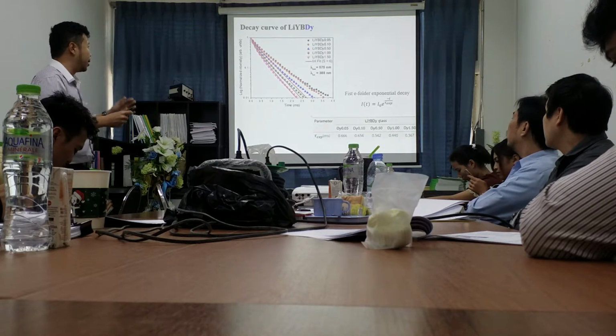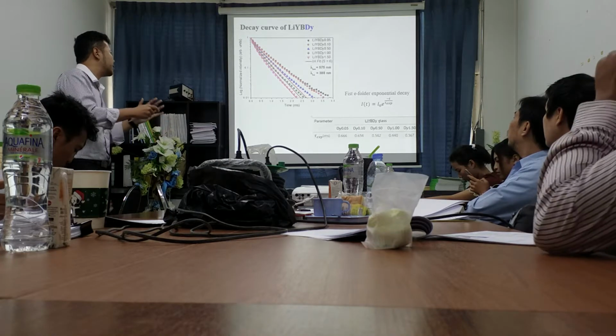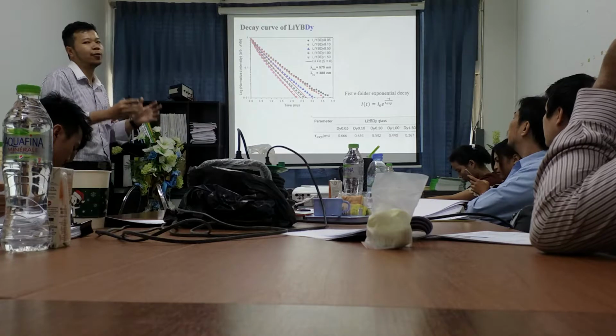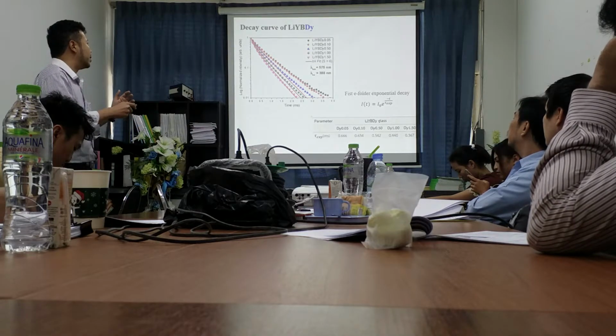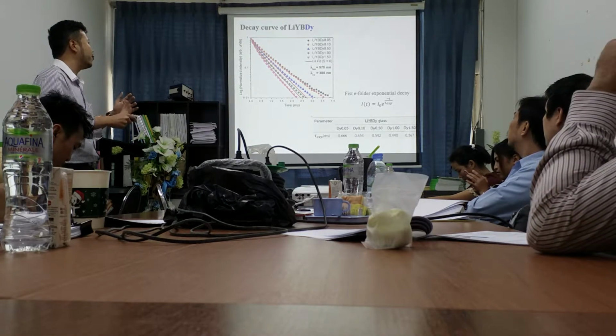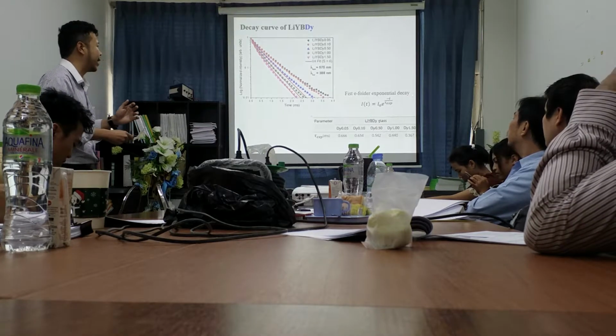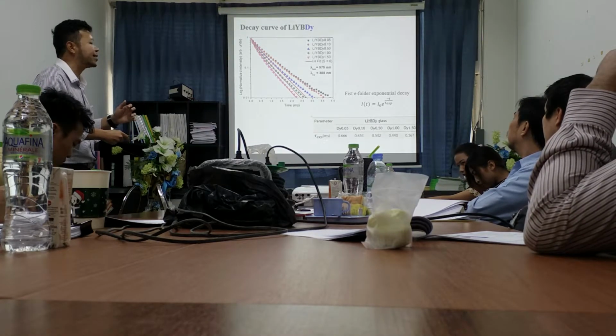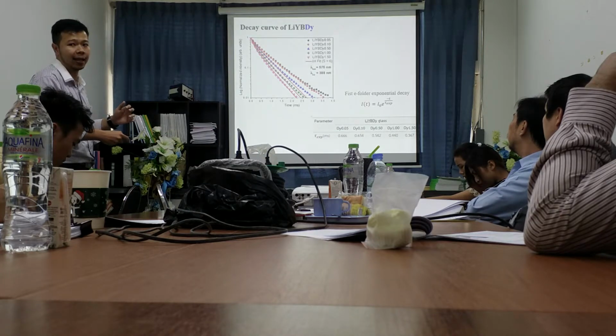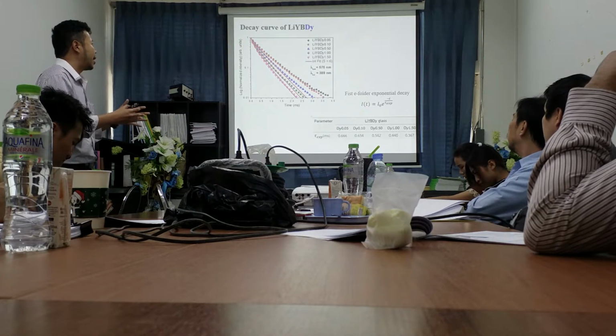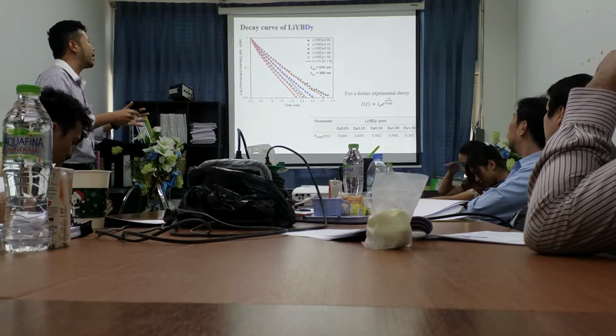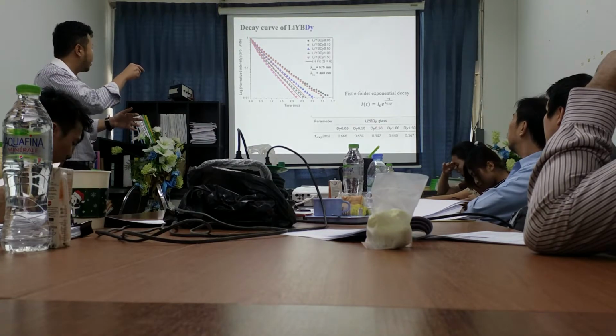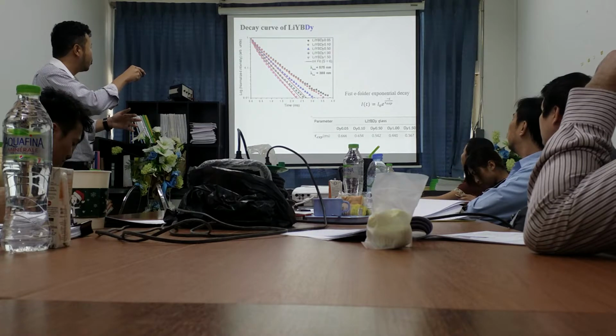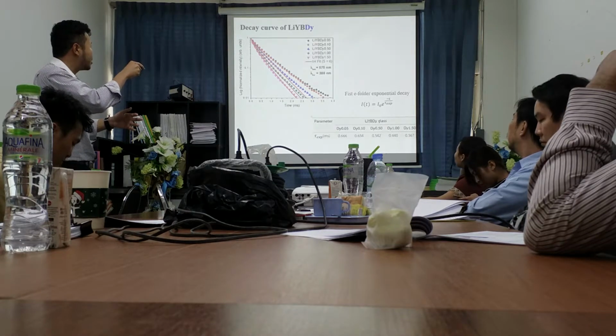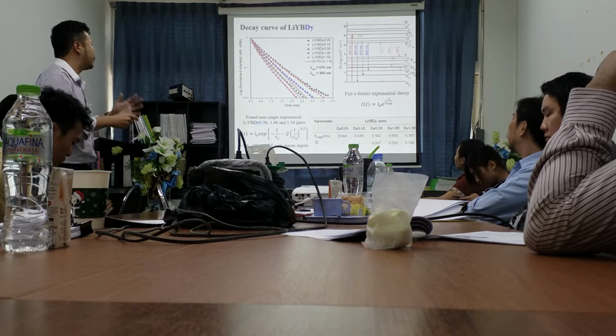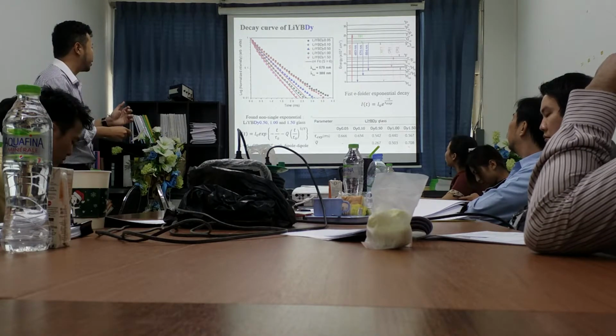Decay curves were measured with the fluorescence spectrophotometer. First, I fit the decay curve with a first-order exponential decay and got the experimental luminescent lifetime in milliseconds. However, I still found non-single exponential decay behavior. These three lines, the blue, green, and pink, are non-single exponential. So I fit them with the IH model to find the Q parameter.